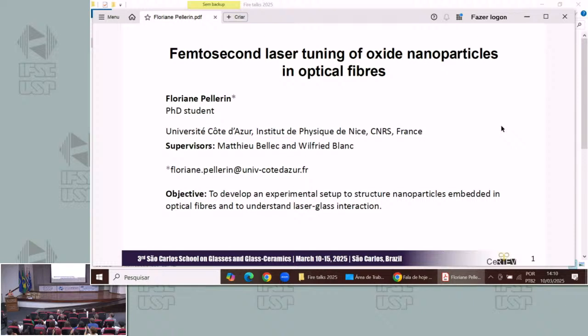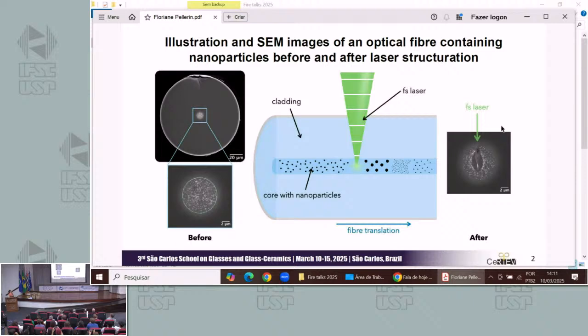My supervisors are Mathieu Bellec and Wilfried Blanc, and I work on the femtosecond laser tuning of oxide nanoparticles contained in optical fibers. So here on the left you have the core of a fiber which contains nanoparticles, and what we do is that we focus the femtosecond laser into the core to heat the material and change the characteristics of the nanoparticles, and on the right side you have a modified core.